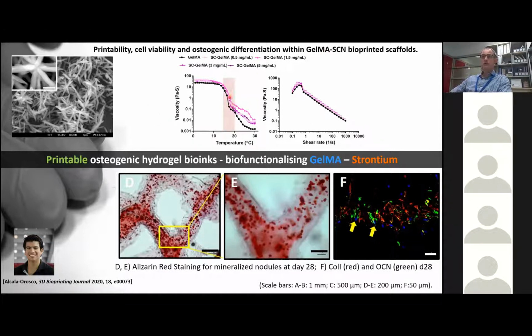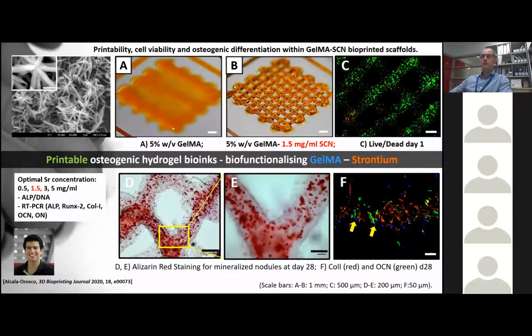We're able to get subtle differences, which can modify the viscosity at the temperatures that we would like to print at, and show that we still have a shear thinning capability, so the viscosity decreases with increasing shear rate. We came to an optimal strontium concentration. If you just take 5% GelMA, a relatively low GelMA concentration, you don't end up with nice print fidelity. The addition of strontium can remedy that, and we can also have good cell viability with the inclusion of these cell instructive strontium nanoparticles.